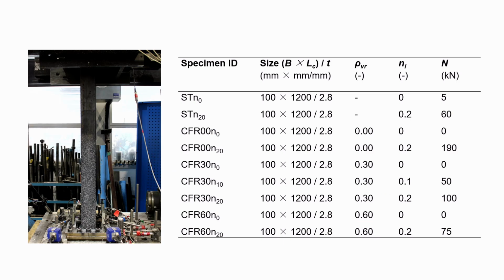So for the specimen details of this particular experimental program, we tested 9 different specimens. We grouped them into 4 groups. The initial 2, the ST there, ST stands for steel tubes. These are just hollow steel specimens for comparison purposes. And then the CF stands for concrete filled, and then the type of concrete infill. So we considered R0 mixes, R30 and R60.